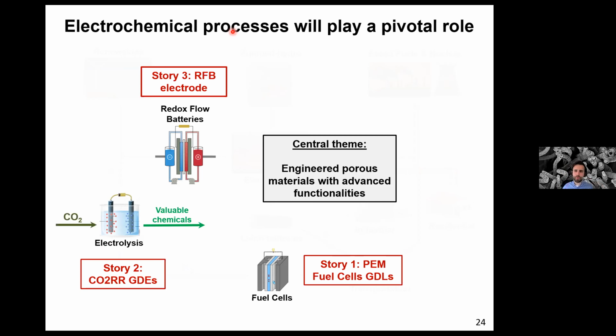To answer from that point of view, you want a material that allows stable operation without flooding for thousands of hours, even at high current densities. As for how, you should think about pore size modifications, even local ones. Perhaps you need smaller pore sizes closer to the areas that can flood, and bigger pore sizes closer to the areas where you want high diffusivity. I also think we need to think about coatings much more, about surface chemistry treatments. Everything is now done with PTFE, and that's great, but I think there is room for more exploratory science there.